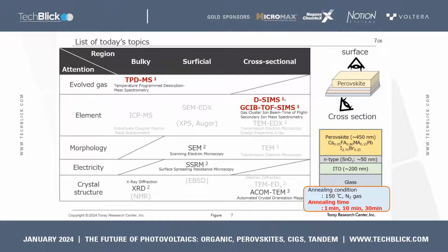The analysis methods shown in the contents are divided by focus points, and are schematically shown in the following table. First, the gases evolved during heating are evaluated by TPD-MS, and the elemental distribution in the sample is evaluated by dynamic SIMS and GCIB-TOF SIMS. For all 4 measurements,